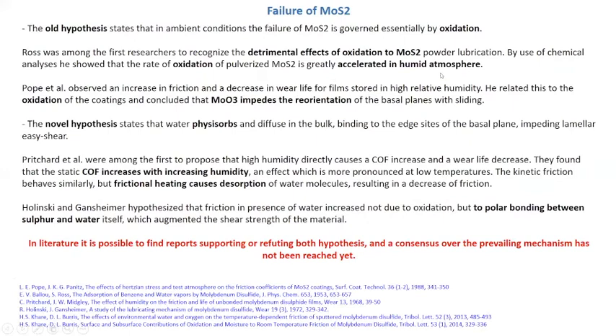Okay, and finally, we have another important issue related to MoS2: the failure of MoS2 in presence of humidity. In this case, again, we have two hypotheses. I call them the old one and the novel one. The old one foresees that the presence of humidity induces the oxidation of the material, and in particular the generation of MoO3, which is an abrasive material, and the generation of these oxides induces the progressive failure of the coatings in presence of humidity.